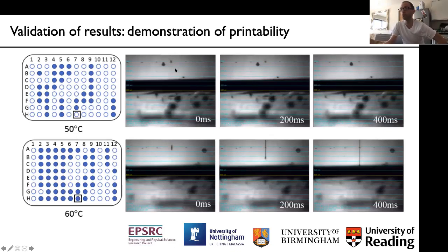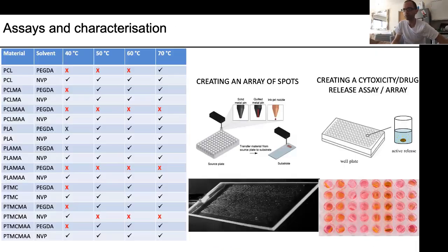And so on the right, you can see up at the top, this black blob at the top is the nozzle, a print head nozzle. And you can see in the upper scheme, there's nothing coming out of this nozzle. It's a no-no. It's not printable. And then in the bottom row, we can see a thread of material that comes out, showing that it's ejectable, it's printable. And so this was our litmus test and showed that our screening method was predictable and a good guide to whether something would be printable with inkjet. So we went on with this.